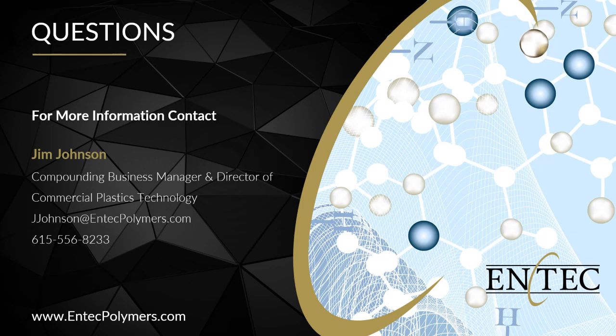Another question here, what non-reactive compatibilizer would you recommend for polyethylene and polyurethanes or polypropylene and polyurethanes? Well, for a reactive one, I would recommend one with maleic anhydride. But the question is, what would I recommend from a non-reactive? In that case, I would tend to lean toward the acrylate copolymers because they'll have very good compatibility with the polyethylene and polypropylene, but they'll also have the acrylate functionality that will work with your polyurethane. So in that case, I would look at one of the acrylate copolymers to utilize for that.